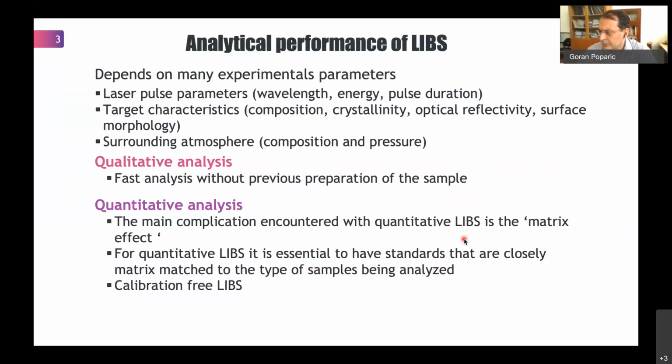In the case of quantitative analysis, we have a main complication induced by the matrix effect. This effect can be reduced by using matrix-matched samples for the construction of calibration curves, but these types of samples are not easy to obtain. The other approach that can be used is known as calibration-free LIBS. It uses some mathematical approaches, but it cannot be achieved with our LIBS setup.